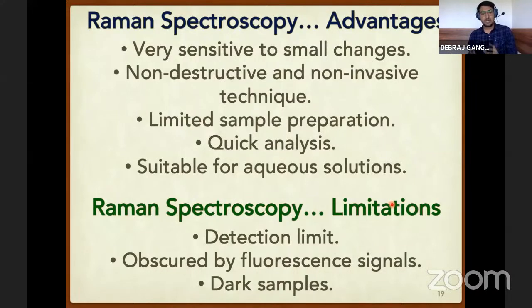The third thing is that it requires limited sample preparation. In fact, we need very little sample for recording Raman spectra, and it's possible to prepare the sample very easily, unlike some other techniques like FTIR spectroscopy, where specific sample preparation is needed for recording the spectra. The analysis is very quick. You have the Raman spectra in front of you, and if you can assign the bands, the analysis is pretty easy. And it is suitable for aqueous solutions, unlike IR, which is not suitable for aqueous solutions. Raman is very suitable for studying aqueous solutions.